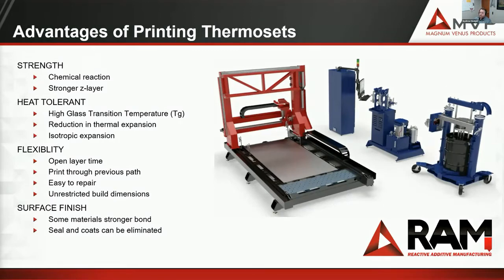Because again, you're cross-linking these materials, and as they're curing, the materials are bonding together. There's a reduction in thermal expansion, and some of these materials have isotropic expansion. So depending on what your end use cases are and what you need to do this for, there are different materials that work for different products. The biggest flexibility, as you'll see as we go through this whole presentation, is the open layer time. And that's probably one of the major advantages to thermoset printing. You have the opportunity to actually print through previous paths when you're printing on this machine as well. So you don't have to go bead side by side. You can actually print through the previous path because it's still liquid until it cures.